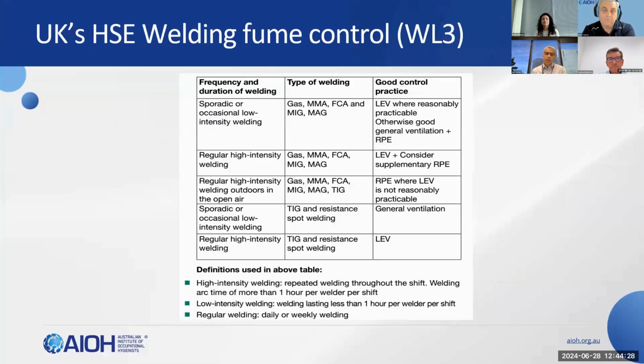The UK HSE's welding fume control WL3 document is a very good document that's worth looking up. It has this table in it that I thought I'd highlight, and it's quite consistent with the way we've instructed our inspectors. And if you notice at the bottom there, it's talking about 1 hour per welder per shift.